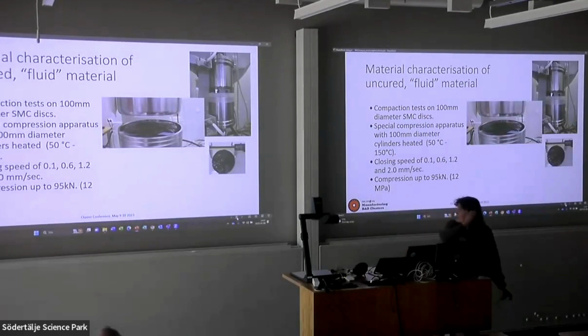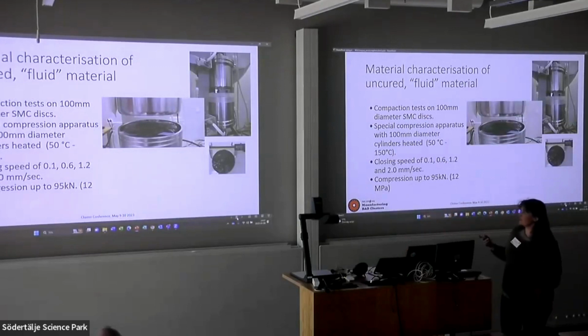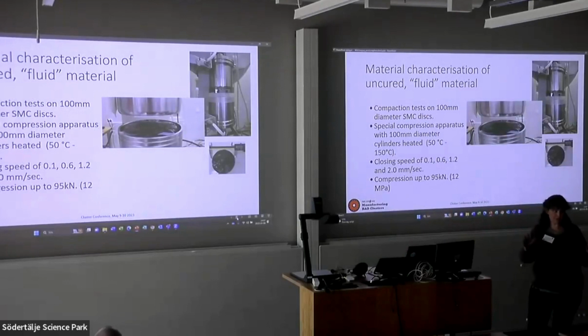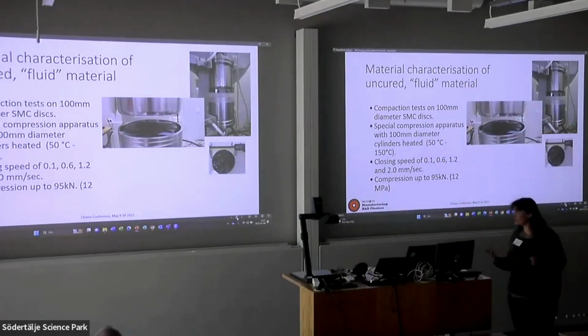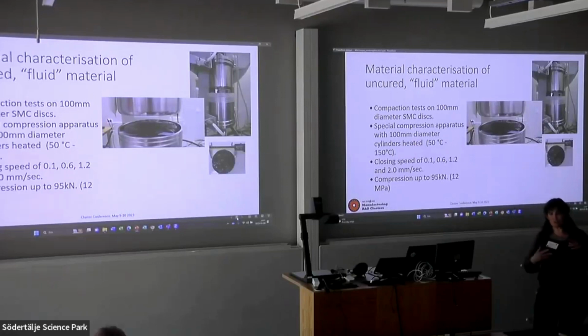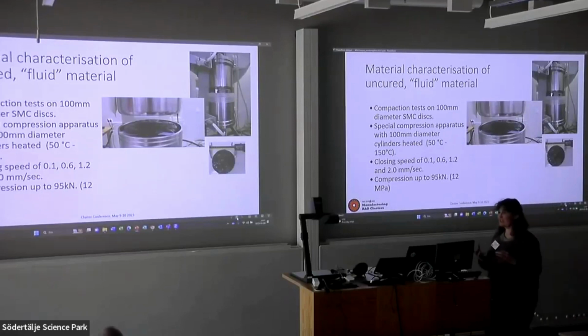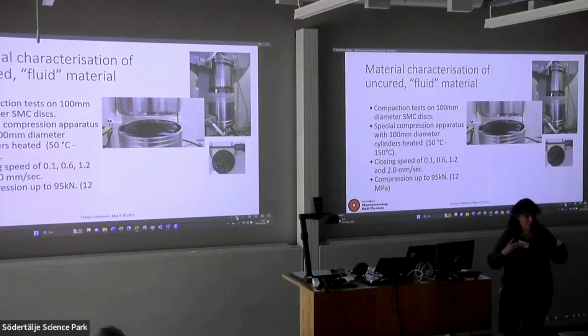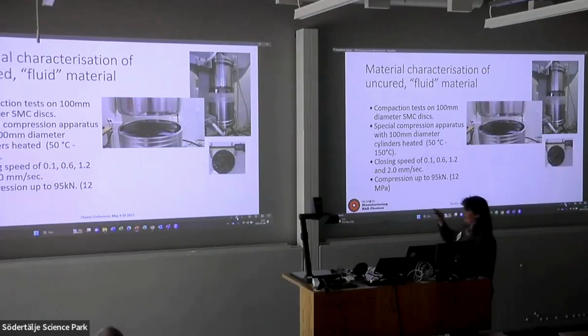So for the material characterization of the uncured and fluid material, basically we're just looking at squeeze tests. And the reason that we're choosing squeeze tests as opposed to other types of measuring rheology is because the way in which you're testing is very similar to the way in which it's being manufactured. So this way we can characterize it, even though we're characterizing it as a fluid and it's not a fluid, we have much closer models or parameters for that behavior. So this was found to give us better results.